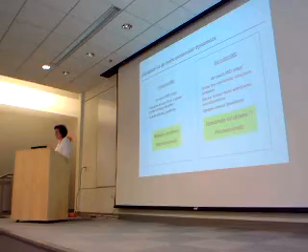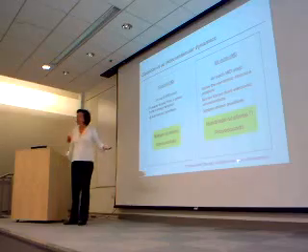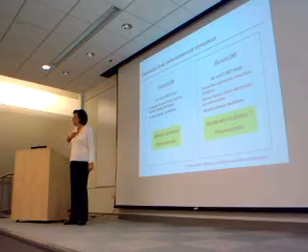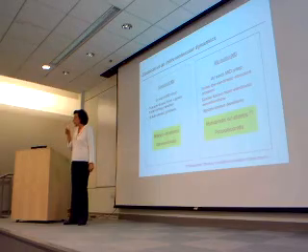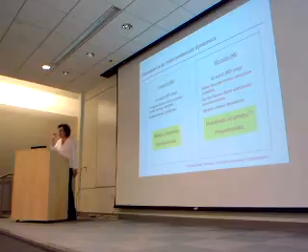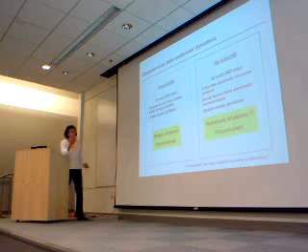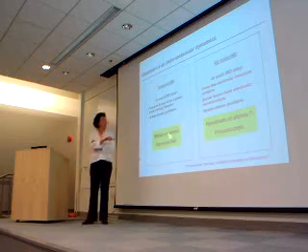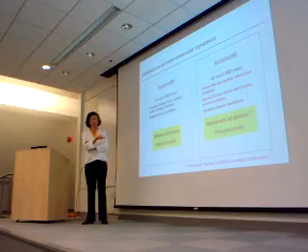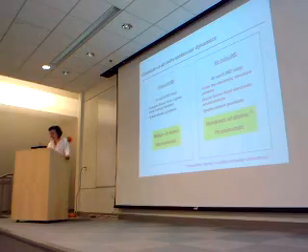But please, when we talk about what can be done with ab initio molecular dynamics, always remember that the key variable is really the number of electrons. Okay? Simulating sodium with only one valence electron is very different from simulating fluorine or oxygen with six valence electrons. So it's not the number of atoms; it's really the number of electrons that matters when we talk about molecular dynamics. But roughly, to have an idea, here millions of atoms and nanoseconds, and here you are down to hundreds of atoms and picoseconds. So different kinds of systems, different time scales, and also different kinds of error bars.